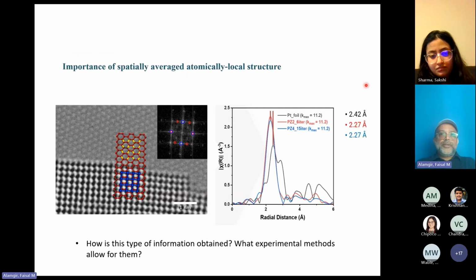So here's a different example. Now we're stepping away from batteries, and we're looking at what would be a catalyst for a fuel cell. So the question here is, what is a local measurement that we need there? In this particular case, we were doing a study of the atomic structure of platinum atoms as they are grown as a film on top of graphene. The fact that it was growing on top of a film is something that we intuited from several other methods, but the first time that we were actually able to image this and show it directly was with this electron microscopy image that you see on the left.